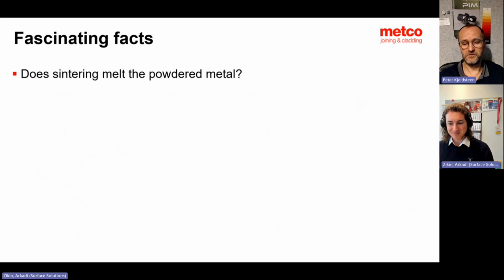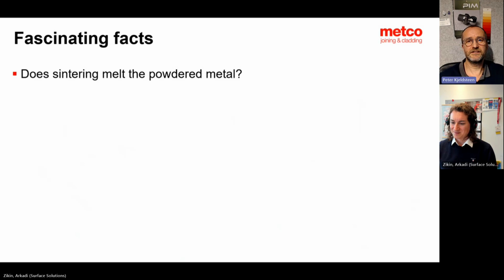You can say furthermore, it typically doesn't have the right size, because during sintering, it also shrinks. Correct. So a typical shrinkage rate is 2 to 4%. So therefore, we make it typically in oversize. I remember calculations in my master classes for powder metallurgy: find out the shrinkage rate of titanium carbides and some kind of binder.